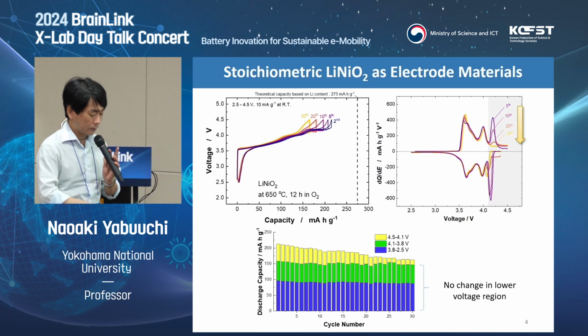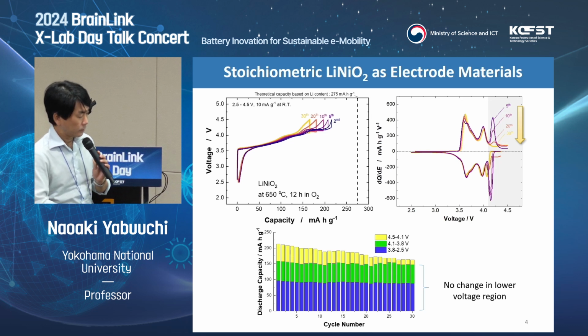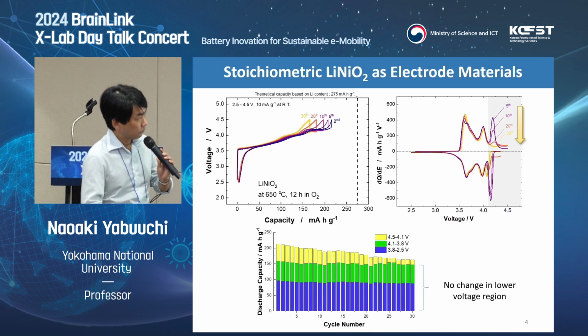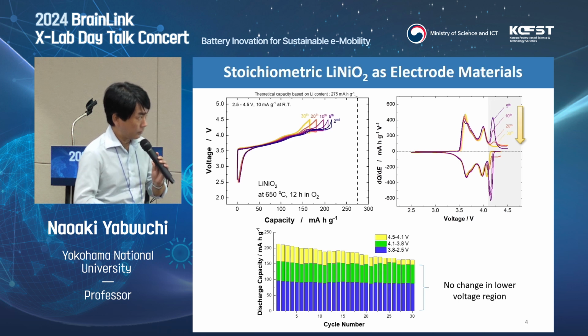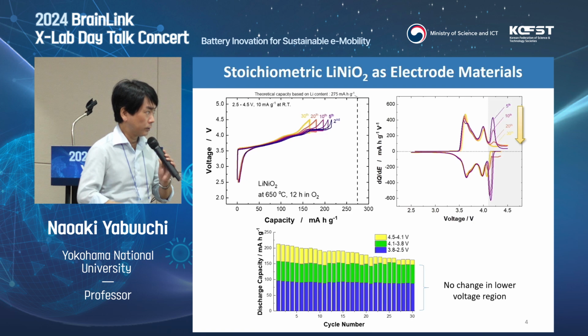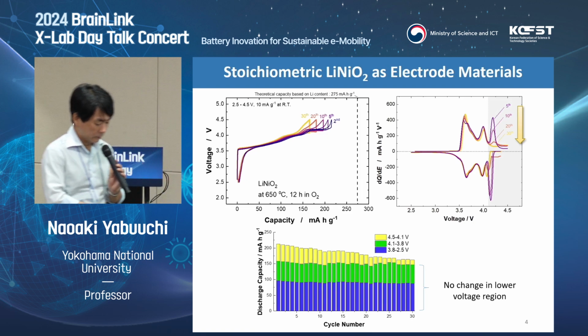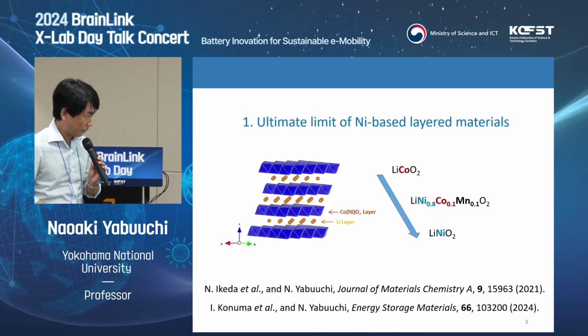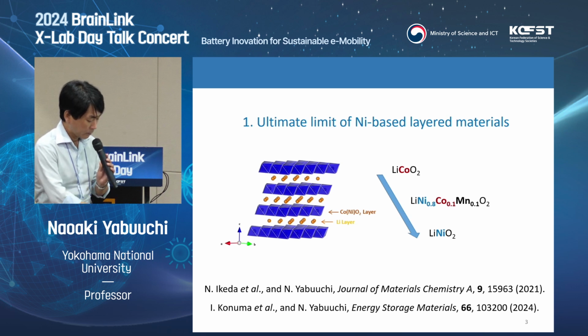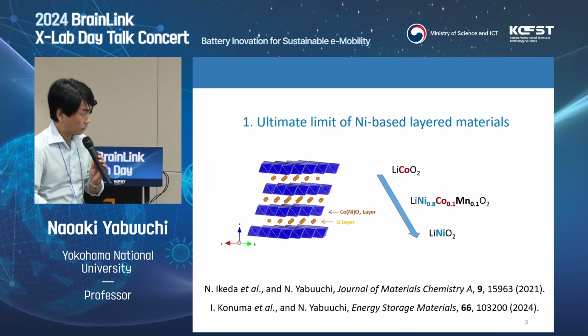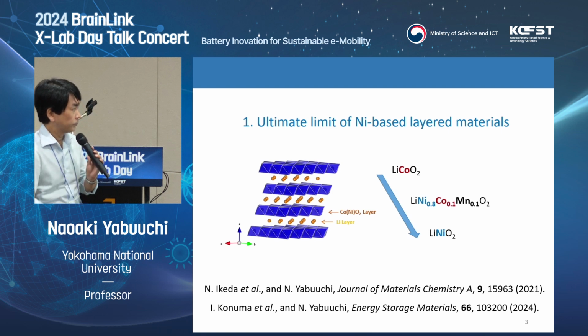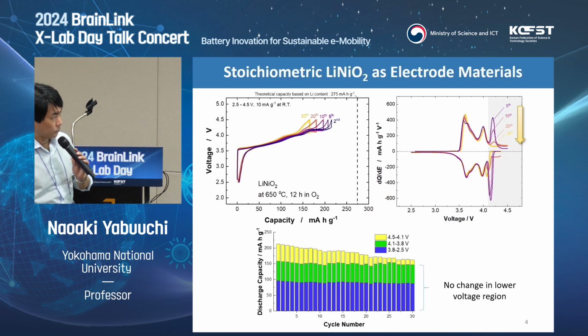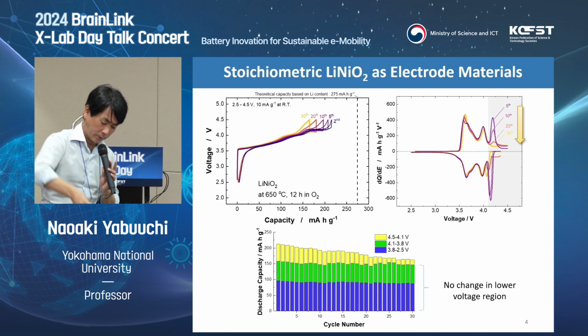Many people discuss material fracture associated with volume changes. In that case, isolation of electrode materials results in capacity loss over the entire voltage region. However, this degradation process is very, very unique, observed only in the high voltage region. We also discuss in detail the origin of this degradation process. In summary, it is caused by surface degradation, and upon charging, nickel ions migrate to tetrahedral sites. The nickel ions cannot migrate back from the tetrahedral sites, leading to accumulation of impedance at the surface.